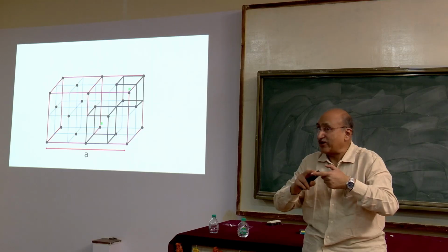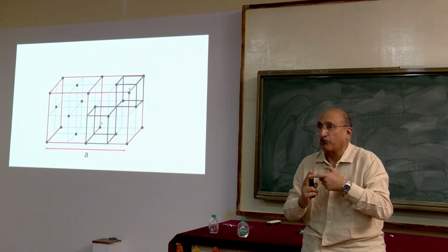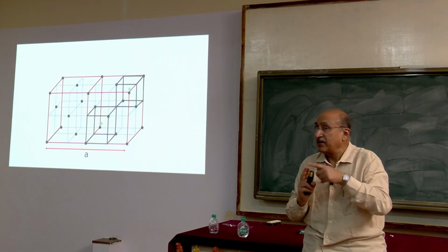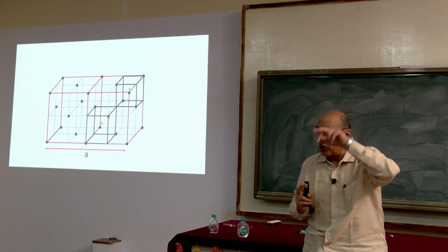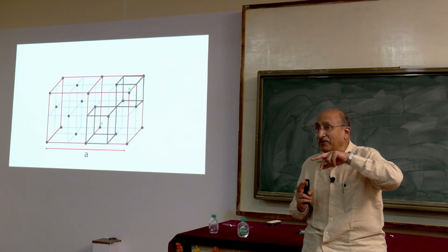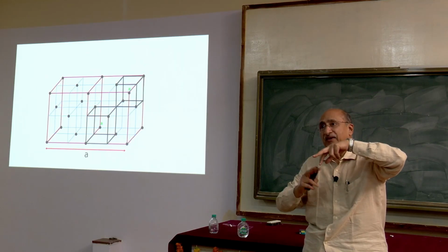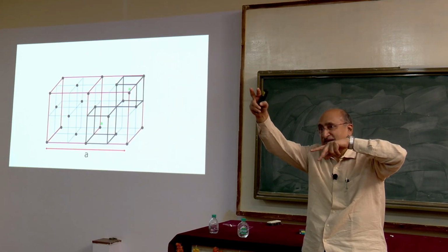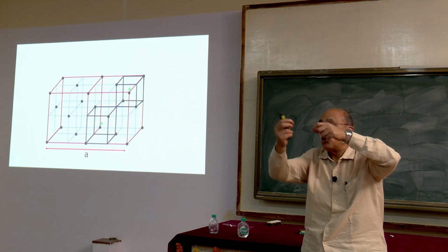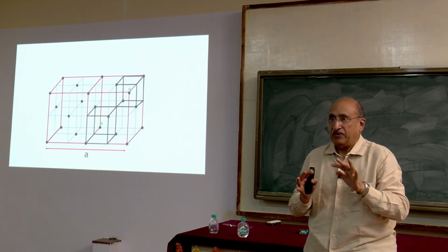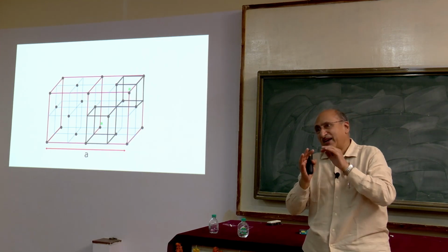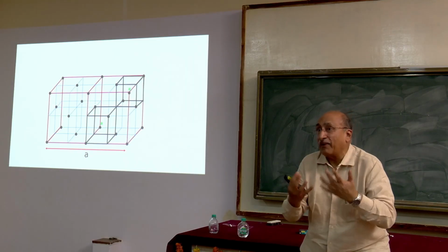Though there is evidence, for example, I gave you two examples: Fe3O4, which at low temperature becomes a non-cubic structure, and copper ferrite, which at room temperature is supposed to be tetragonal and at high temperature cubic. When you cool it, you can retain that high temperature structure even at room temperature. So it's possible, but generally not very commonly seen.